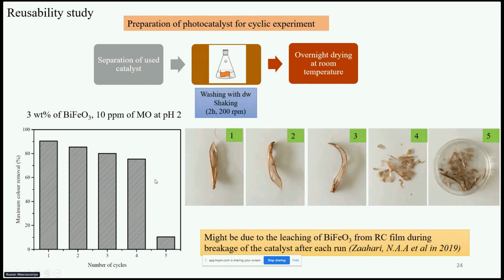So the graph shows the color removal efficiency variation with the number of cycles at each repeated cycle. So it can be observed that color removal efficiency is reduced with the number of cycles, and according to the images, it can be observed that the catalyst has become fragile at the end of the fourth cycle, and that is the reason for the observed significant reduction of color removal efficiency at the end of the fifth cycle. This might be due to the leaching of bismuth ferrite from the RC film during breakage of the catalyst when it is subjected to continuous magnetic stirring.